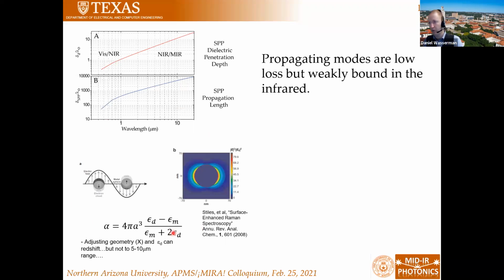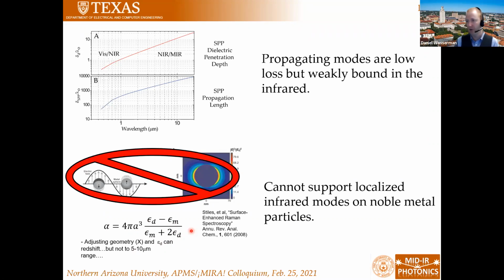If you look at the localized surface plasmon, and this is the response for the polarization of your plasmonic particle, you can see that the denominator here will go to zero when the permittivity of your metal is negative and approximately equal to negative 2 times the surrounding dielectric permittivity, right? But if your metal permittivity is negative 10,000, that's not going to happen. So you can't actually support these modes on a noble metal particle at the long wavelengths where you have these large negative permittivities. So all of the cool stuff that we want to do with plasmonics in the mid-infrared, you cannot do with traditional metals.